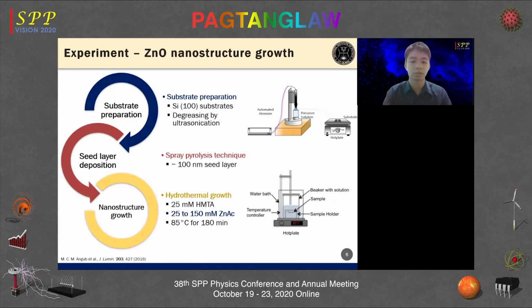At NIP, the zinc oxide nanostructure samples were fabricated on seeded silicon substrates by hydrothermal growth method. The substrates were first degreased through ultrasonication and were deposited with 100 nanometer zinc oxide seed layers by spray pyrolysis technique. For nanostructure growth, the aqueous solutions of both hexamine and zinc acetate were initially prepared, wherein a fixed 25 millimolar concentration of hexamine was mixed with 25 to 150 millimolar concentrations of zinc acetate. The seeded substrates were then submerged into these solutions and heated at 85 degrees Celsius for 180 minutes.